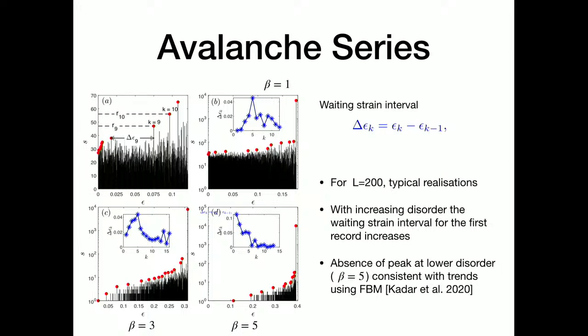The first record here has minimal strain required, which is this one, and then as you go to the next records, you require more and more strain, but the intervals become larger. Then you have the peak corresponding to that, and then you have speed up, acceleration. And the one in between, so here we see a peak formation and then acceleration. Here you see only acceleration for the low disorder, and this is for beta equal to 3. You do see a peak, but the first record happens a bit later than what it was here. So it's in between these two types that you see in the extremes.